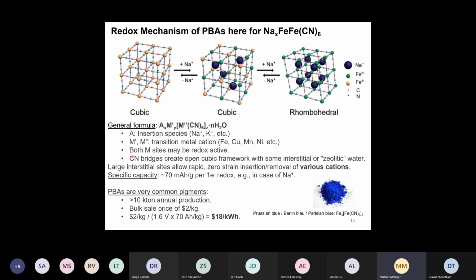And we already mentioned these cyano bridges, these CN bonds that create this open cubic framework structure. And yeah, there can be interstitial, also called zeolitic, water in these materials. And really a big advantage of this structure is that these large interstitial sites allow a very rapid insertion and removal of ions, also in a zero strain fashion. If we intercalate this material up to this stage, then we would get roughly 70 milliamp hours per gram for this 1 electron redox with sodium intercalation.